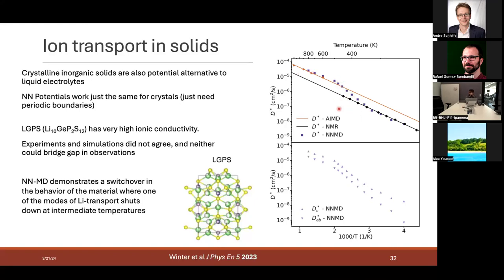But in between, there's a phase transition where the mobility changes. This thing is three-dimensional. There's a Z direction and a degenerate XY direction. And lithium can move along both. But the XY direction has a higher barrier. So that mechanism shuts down earlier at lower temperature. So what we see is this phase transition between fully mobile lithium at high temperature and lithium mobile only on the Z-axis at low temperature. And this difference is pretty much the entropy cost of freezing down the XY plane.